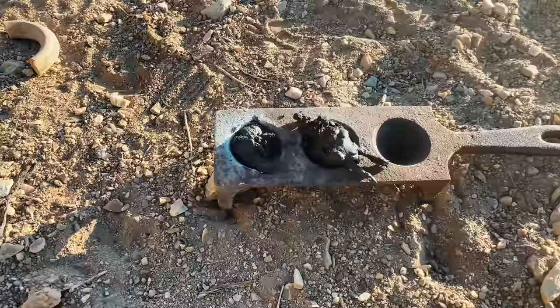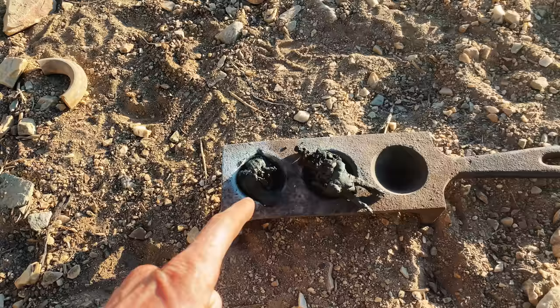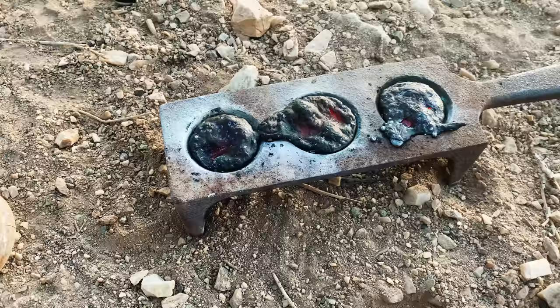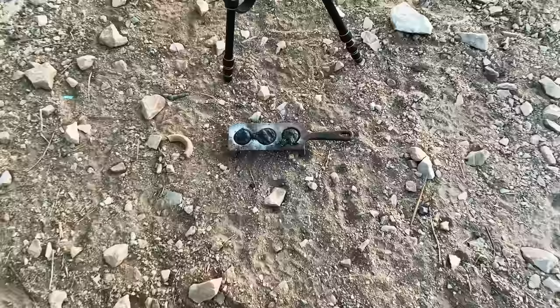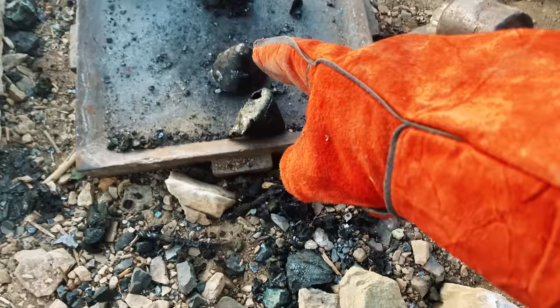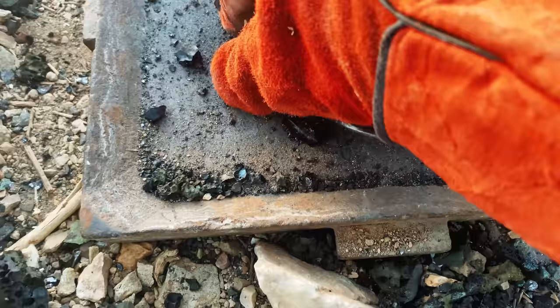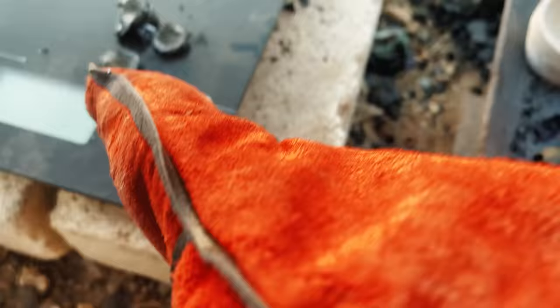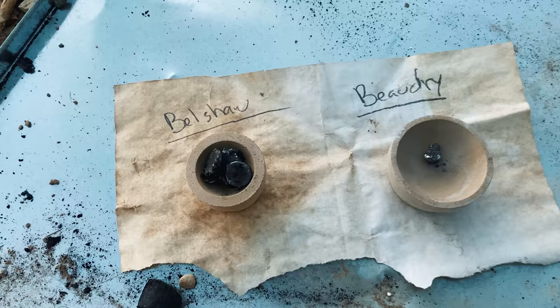That is the result of the Beaudry re-smelting — not an ideal situation, but there might be a little silver in that. And so this is the Belshaw slag — coming over here to the Beaudry slag, Beaudry didn't get it all because if you look at the very bottom, that is lead and silver that was left behind. Now we're going to see if Belshaw left any behind in his slag. They both left some behind — Belshaw might have left a lot behind. That's a lot of lead. Belshaw, they're leaving money on the table. This times 28 tons per day — there's a lot of lead that was left behind.